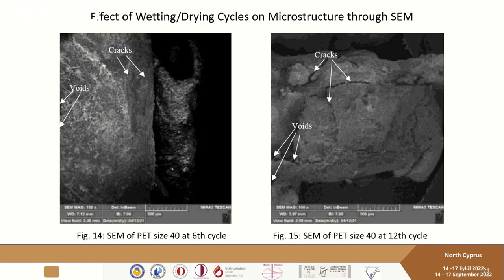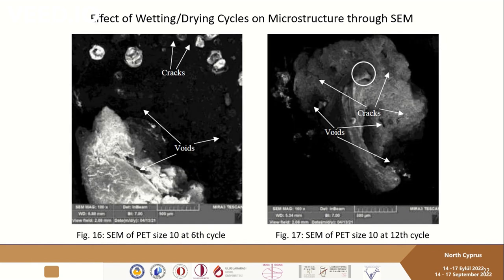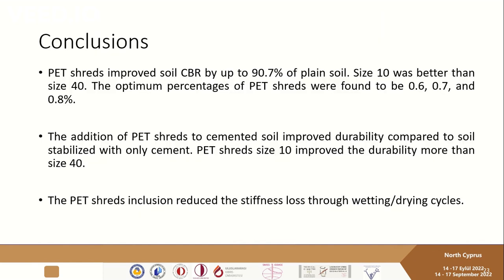Also, if we consider the effect of wetting drying cycles on microstructure through SEM, we can see that the intensity and the size of the cracks and voids was getting increased by subjecting samples to more wetting drying cycles. However, if we consider samples with PET shreds size number 10, we can see that the intensity and the size of the cracks and voids was much lower than in the case of the samples with PET shreds size number 40.